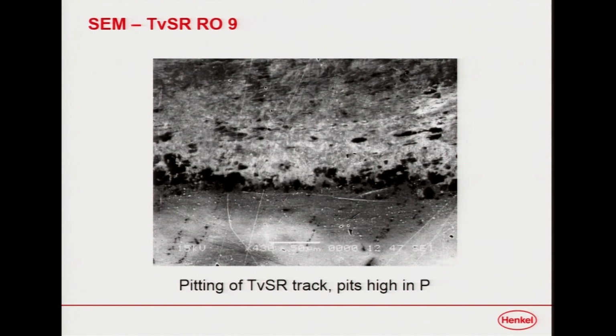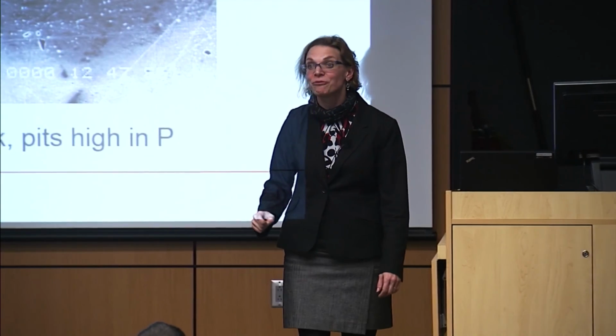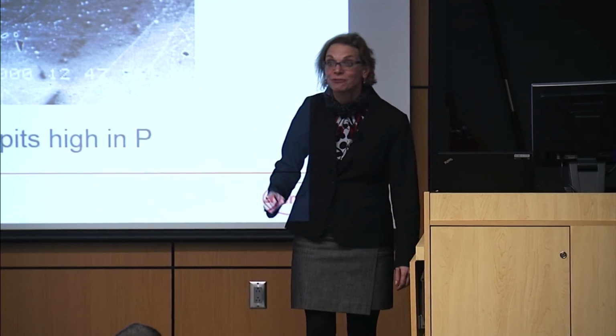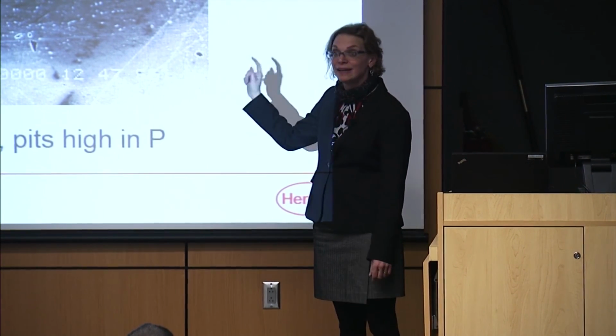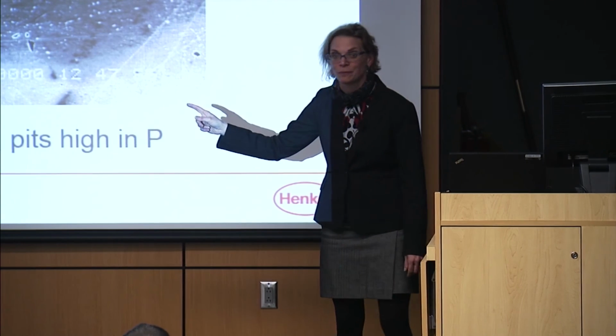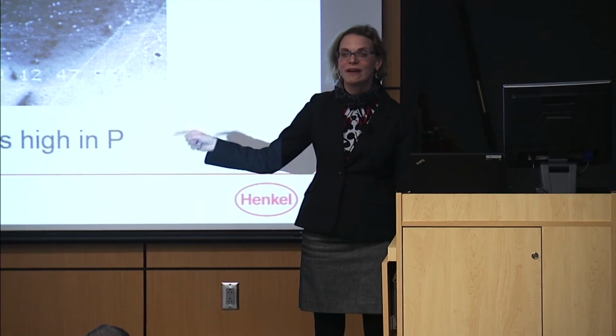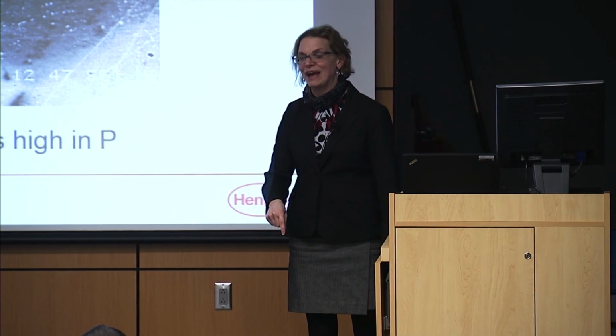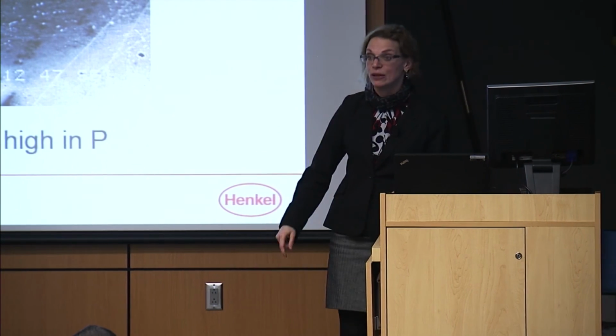And those holes were extremely high in phosphorus, in inorganic phosphorus, no less. Even in the most lightest weight boundary lubrication condition, we had succeeded in pulling the phosphorus off the phosphate ester. We decomposed the phosphate ester in the frictive contact. And that is why a lot of phosphorus in your engine oil is bad for your catalytic converter, because it will come off.